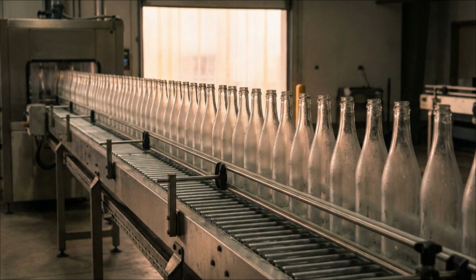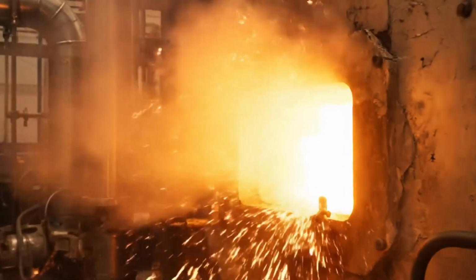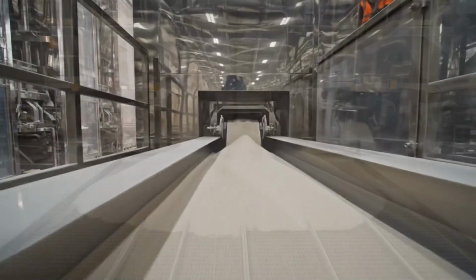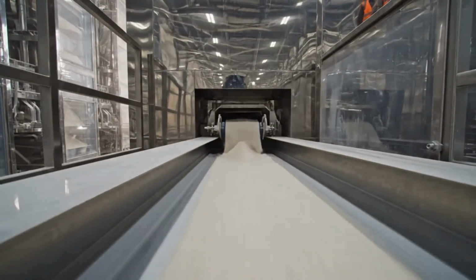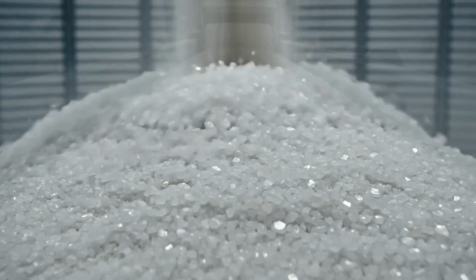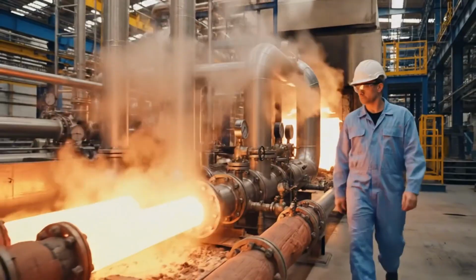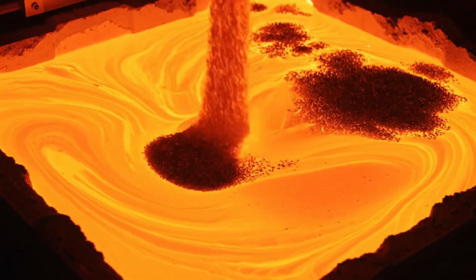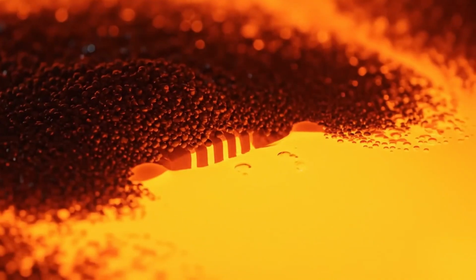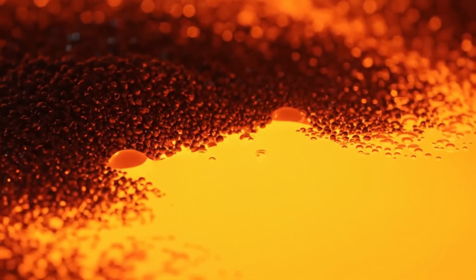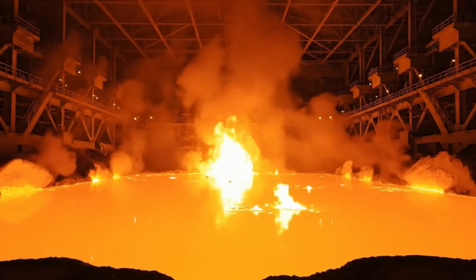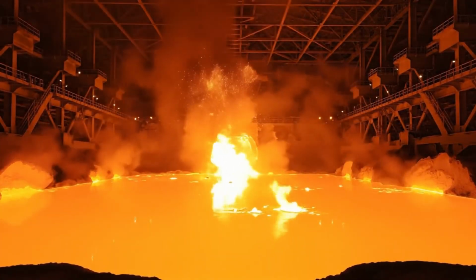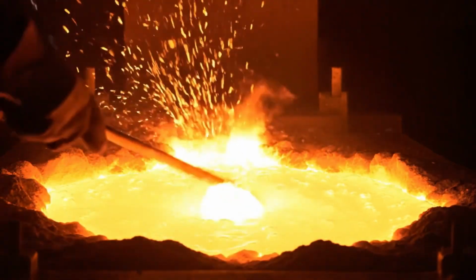Glass bottles look simple, but each one survives 3 invisible systems. First, the batch. 99% pure silica sand mixed with soda ash and cullet, recycled glass, at 40 to 70% of the total. Adding cullet cuts energy use by 40%. Second, the melt. A 24-hour residence inside the furnace where controlled convection sweeps bubbles to the surface. Third, the forming line. Molten gobs drop at 1,100 degrees Celsius, approximately 2,012 degrees Fahrenheit, into molds, shaped by compressed air in under a second.